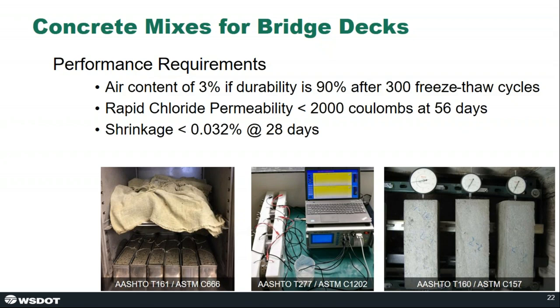We also require a shrinkage limit for our performance specification. That shrinkage limit is 0.032% at 28 days. There are some specimens shown on the bottom right there. It's basically measuring the length change after 28 days where the concrete specimen is exposed to drying. And the shrinkage limit is two or three times less than what you would typically expect out of our old concrete mixes for bridge decks.